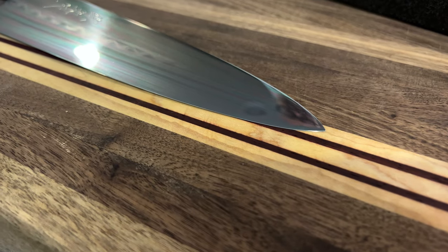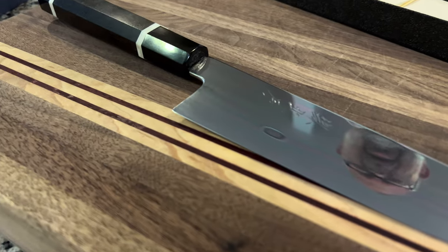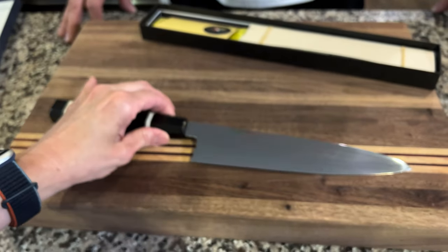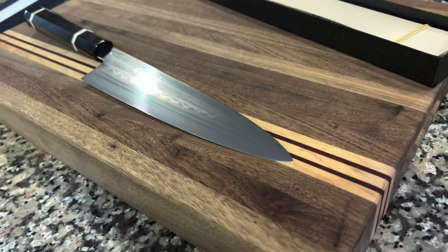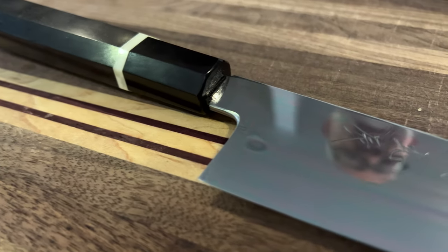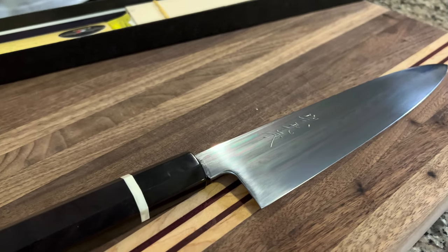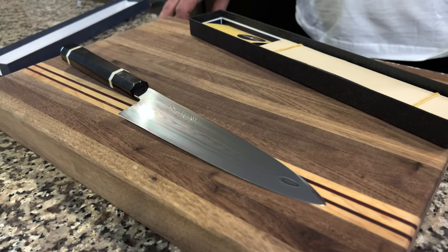This particular knife is made of white number two steel. There are only four blacksmiths in the world that make honyaki knives in white steel. If you see the wavy line down the middle — what you need to know is when this knife is heat treated, the knife is first put in the heat to reach a certain temperature, and then clay is bonded to the spine of the knife. That clay will insulate the knife when it's heat treated again, so the edge of the knife is heated to a different temperature and will have a different hardness than the back of the knife, so the back can absorb vibration and be softer. That wave pattern marks where the hardness of the knife differs.